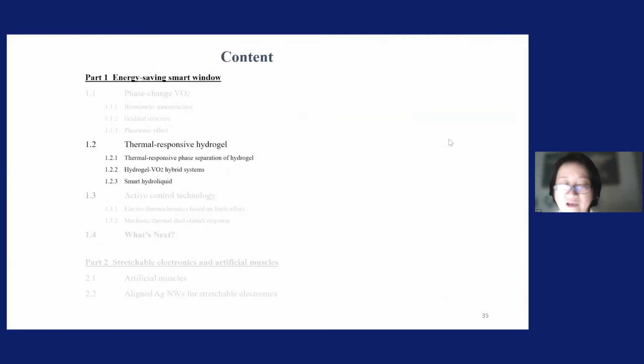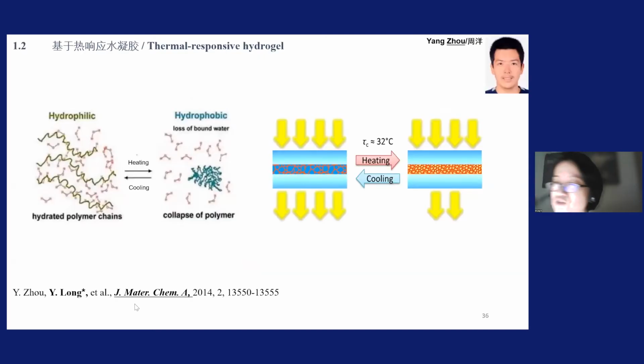Okay, so now I move to the hydrogel. As I said, after 3 or 4 years, we realized, hey, it's really difficult to continue to improve this Tlum and Tsol. So what can we do? Obviously, as material scientists, everyone does organic or inorganic. Maybe we can try organic. So we started from this. The first is a very simple paper. We simply drip hydrogel liquid and then laminate between the glass. And by simply controlling its thickness, we can get all sorts of different optical responses. So this is the very first hydrogel smart window in the research community. This is the first paper.